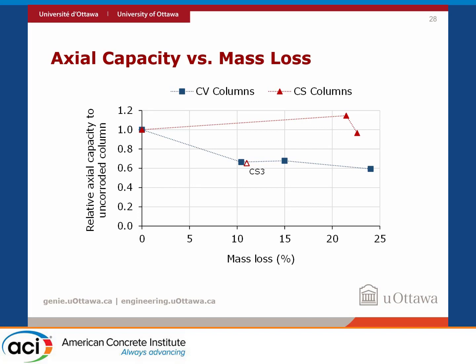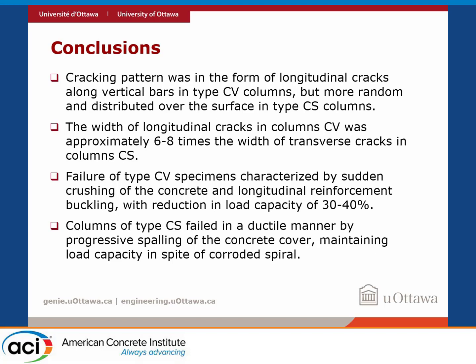So in conclusion, the cracking pattern was different in both types of columns. In the one with the longitudinal reinforcement corroded, the cracking pattern was longitudinal, parallel to the steel, and the crack width resulting from that corrosion was 6 to 8 times that of the transverse cracks in the other types of columns. The failure type of column CV was brittle, with sudden crushing of the concrete and longitudinal buckling. And the columns of type CS, which were confined columns, performed quite well and attained the second peak of strength, even though the spirals were corroded.